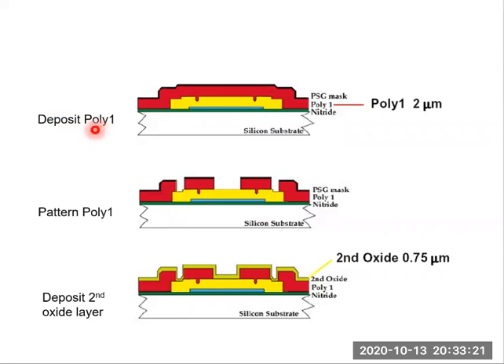Then deposit poly 1. We know that poly 1 is the second polysilicon layer, 2 micron thick. This red layer represents poly 1. After poly 1 is deposited, a PSG layer is also deposited. So actually 2 thin film layers are deposited in this step, poly 1 and PSG layer.